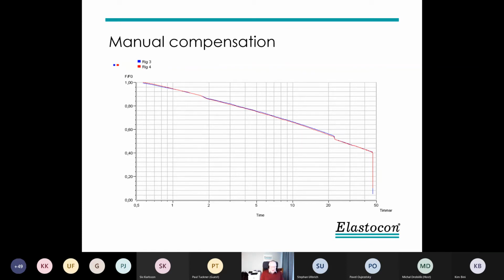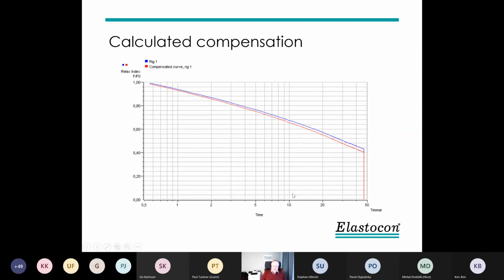There are 3 ways of handling this, which we all point out in our manuals. First, you can disregard it because you run comparative measurements. You have the same error in all measurements. Or you can do a manual compensation. That means on the dial gauge on the instrument, you can see how much this has been, and you can do a compensation there after a couple of hours, after 1 day. Or we have also put in the software a calculation, which makes the compensation. And there is a compensated curve, that's the red one, and the blue one is uncompensated. So without compensation, you get too good results. And with compensation, you get a better, more realistic result. But it's possible to see both of these curves in the software when you do the evaluation, both the compensated and not compensated.